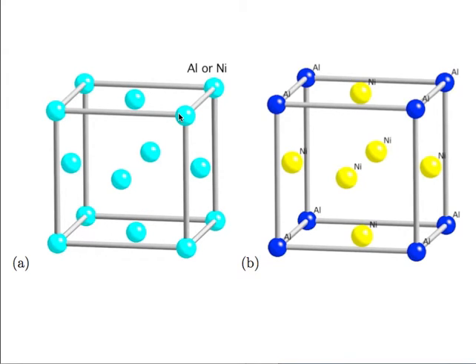But if it becomes primitive cubic - with nickel atoms at the face centres and aluminium atoms at the corners - then you will pick up 1,0,0 because the atoms located halfway will not exactly cancel out the waves from the atoms on the faces since they are different atomic types. So you will get weak 1,0,0 diffraction from that.